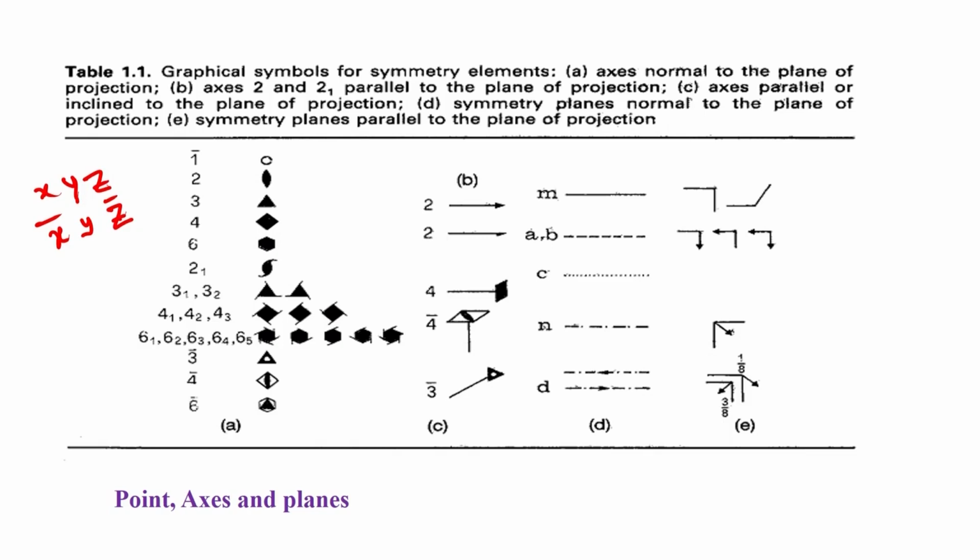And whenever we have these kinds of operations, these operations of symmetry are referred to as point group symmetries. So, a 2-fold symmetry therefore represents an operation on any point x, y, z in space, which can go over to minus x, y, minus z, and that minus x, y, minus z will now go to x, y, z. So, this is the relationship to represent a 2-fold symmetry axis.